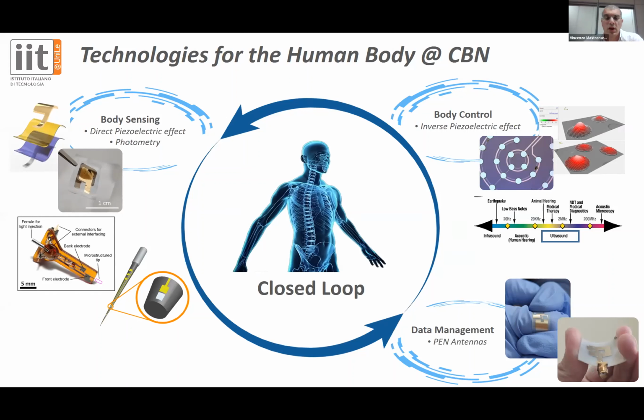So the first application I would like to show you today is our chitosan-based piezoelectric transducers that we fabricate, exploiting also the silver ink of the DragonFly LDM 2.0, in order to have a final transducer that is fully biocompatible. The fabrication process of this flag-shaped sensor starts with the printing of the nano-ink based bottom electrode exploiting the DragonFly LDM 2.0. This electrode, whose thickness is 1 micrometer, is printed directly on a glass substrate.